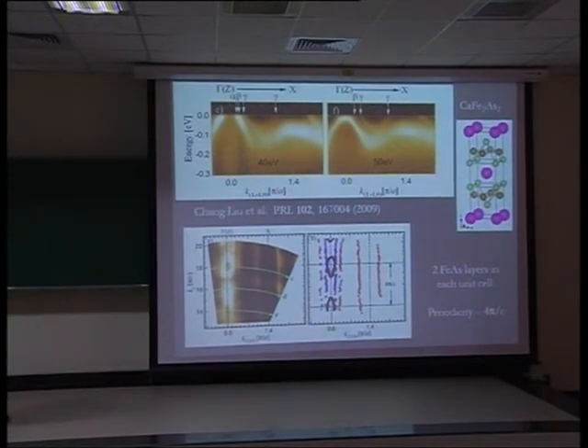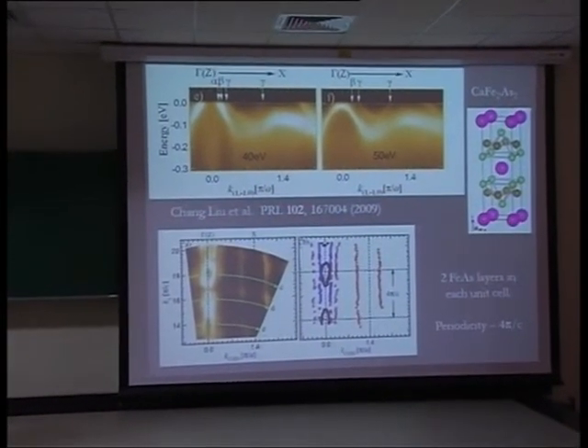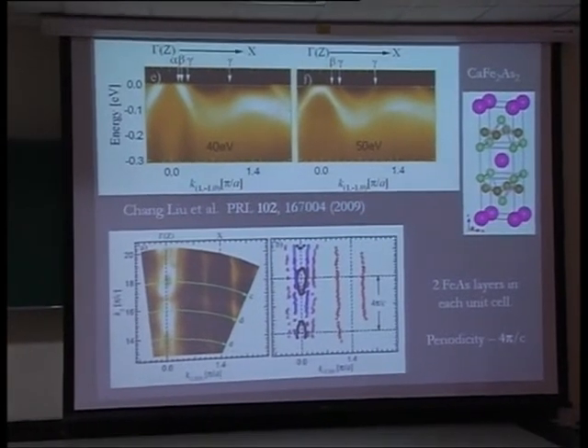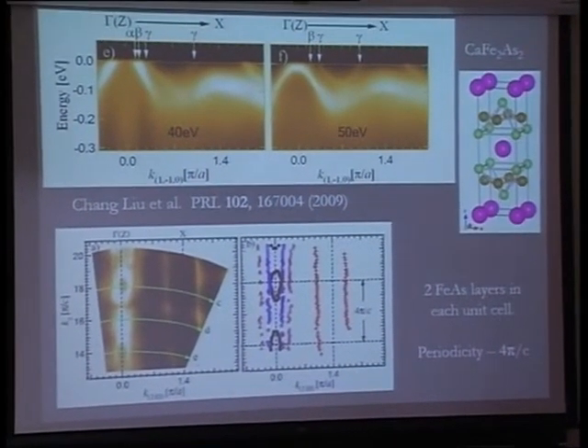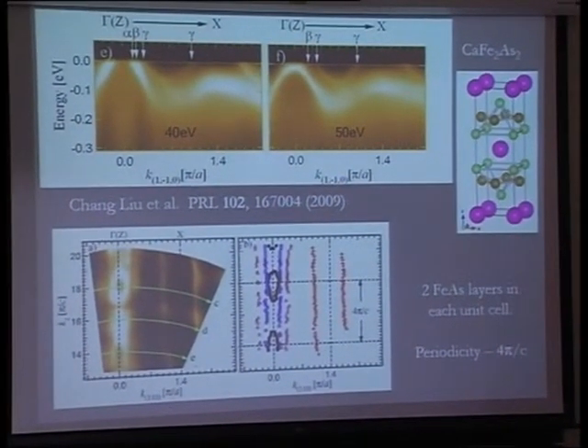So here what you are seeing is that your C is essentially C by 2. So your Brillouin zone boundary shifts to 4 pi by C. Okay? So that's the periodicity that you see. Now if you look at the room temperature spectrum, which is shown in the same paper, you see that the Fermi surface actually looks very cylindrical and effectively 2D.